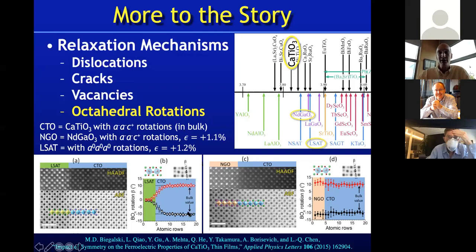I don't mean the bulk of calcium titanate, because this is strained. It's strained by about 1.1%. But it means that it's no longer changing. So you can see that there's a few unit cells, a couple of nanometers, in which the octahedral rotation pattern evolves from that of the substrate with no rotations to that of the steady state film, which has rotation angles, and particularly we're talking about this angle beta, which is one of the in-plane tilts.